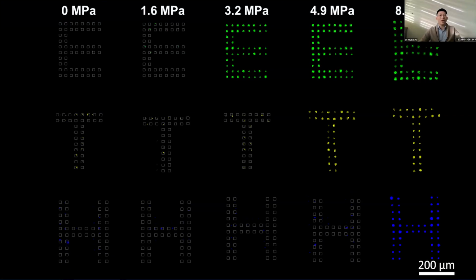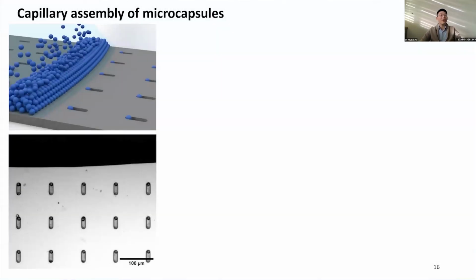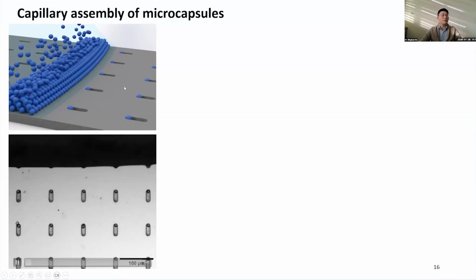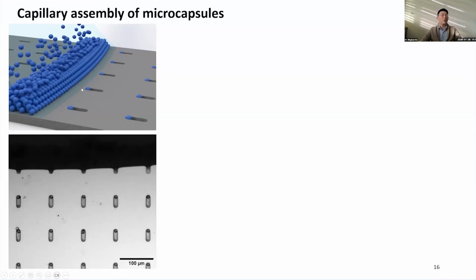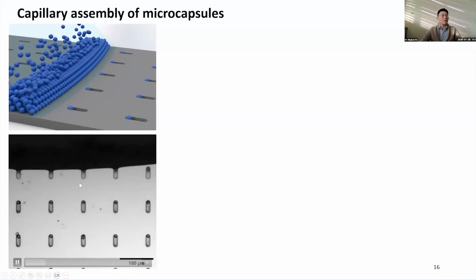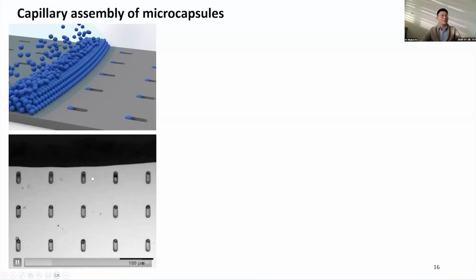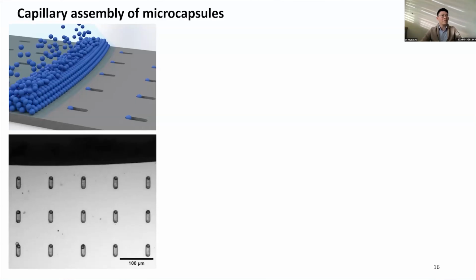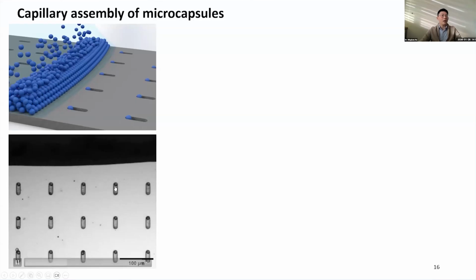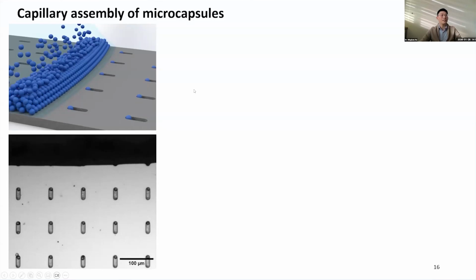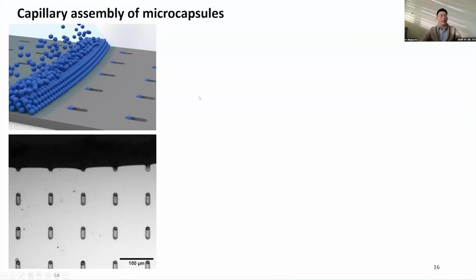But the next step would be how to combine these 3 microcapsules together. And in our lab, we developed a nice capillary assembly technique to do that. Briefly, we first let the microcapsule suspension be deposited on the templates, and then we tune the surfactant concentration as well as the scanning speed. Then we can nicely end up with each trap having 1 microcapsule inside.